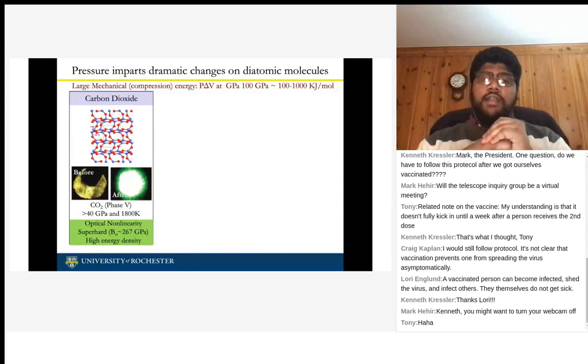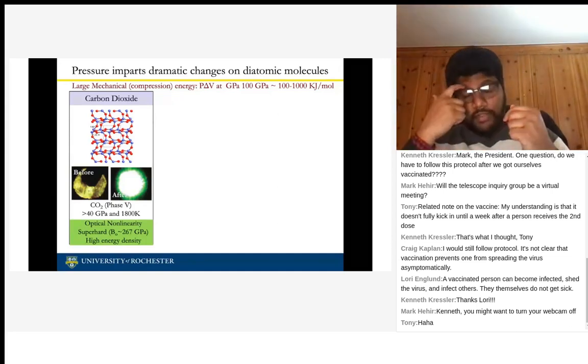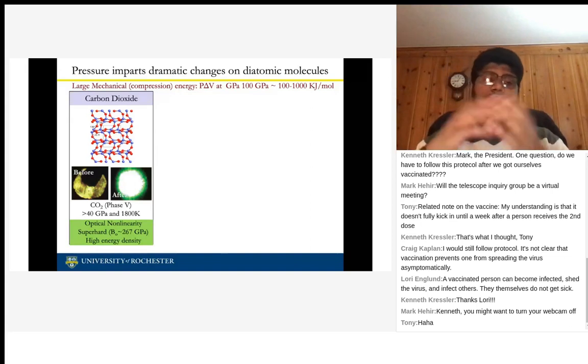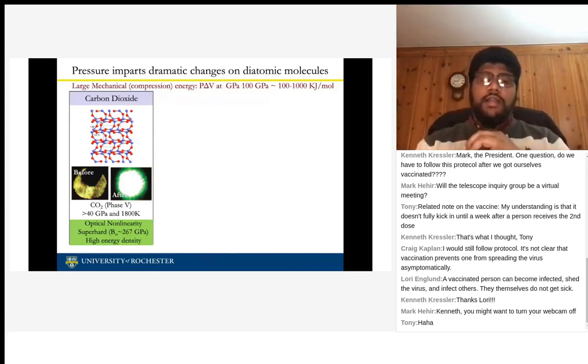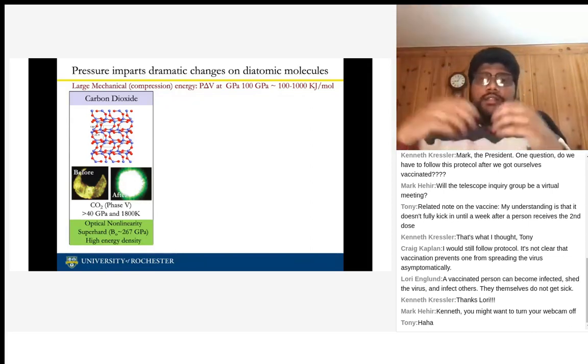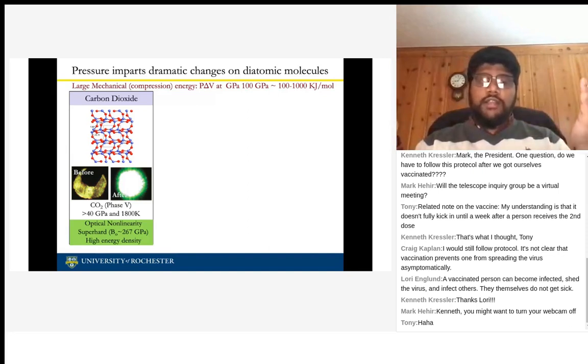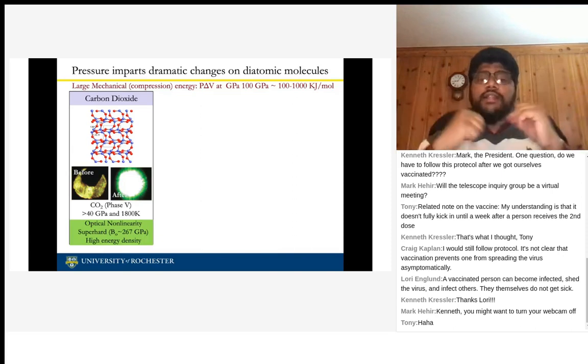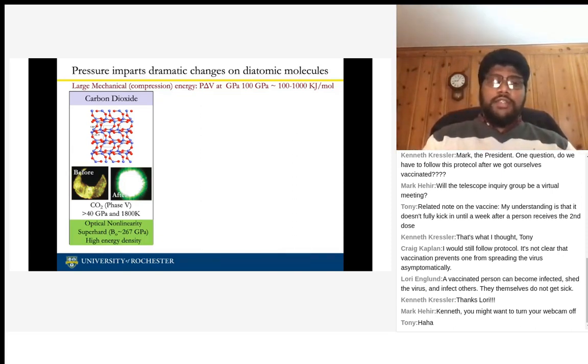And interestingly enough, this material has totally different properties, and it's optically nonlinear. What I mean is that it has a very different response to any optical input. For example, if you shine a 1064 nanometer laser line onto this material, you get green light out. At 1064 infrared, you don't see it. But as soon as you shine that laser light, you get 532 nanometer laser light coming out of the sample.